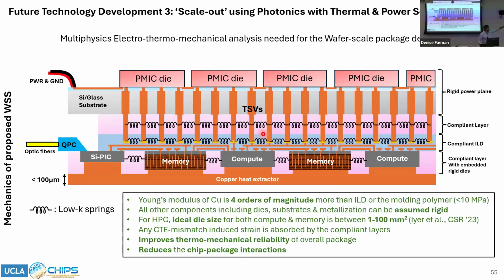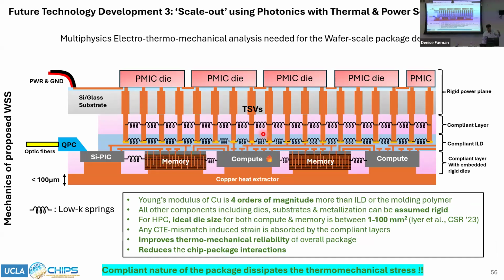And then, why this compliant layer really matters is because if you look at the Young's modulus of copper, it's around 4 orders of magnitude more than interlayer dielectrics or this molding compound. So for all intents and purposes, you can assume that all the metallization is rigid, including the dies, and everything around it is like a bunch of springs. So imagine one of the dies was getting heated, then this die would expand, but the stress of this expansion is distributed among these compliant layers. So it would reduce the chip package interaction and also improve the overall mechanical reliability of this package.